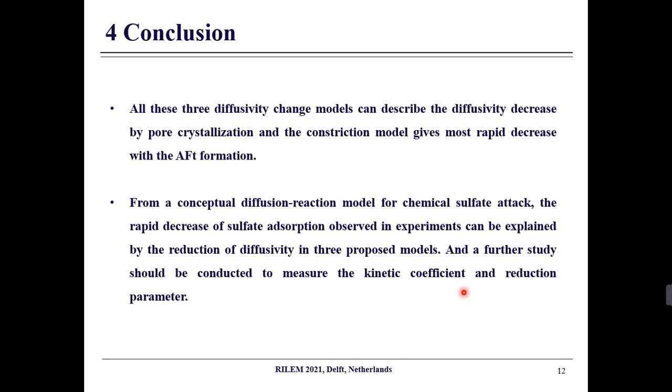Finally, let's conclude. Firstly, all these three diffusivity change models can describe the diffusivity decrease by pore crystallization, and the constriction model gives the most rapid decrease with ettringite amounts.